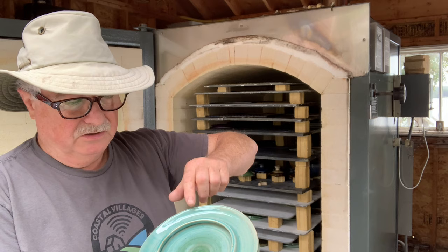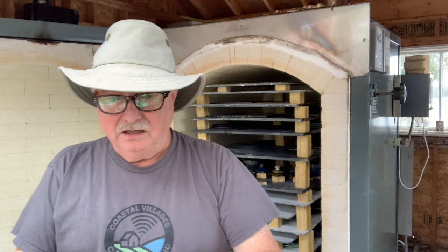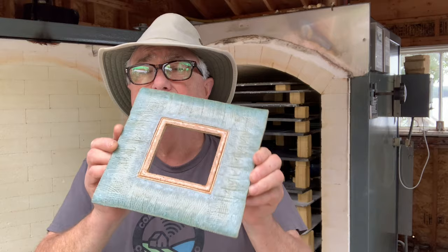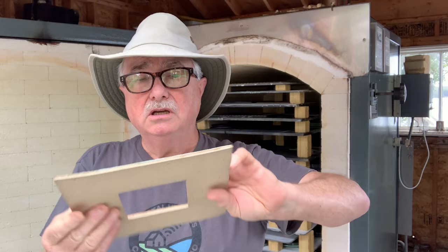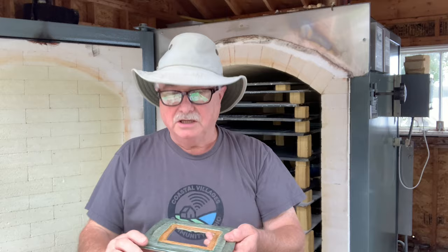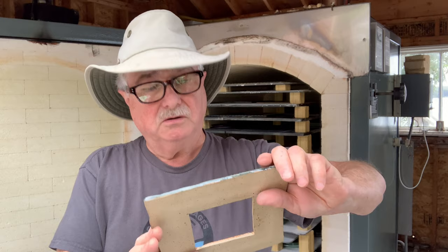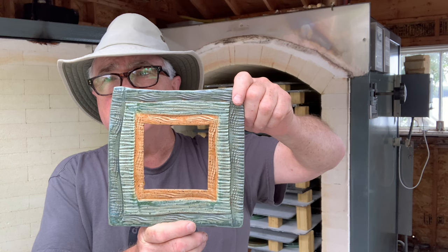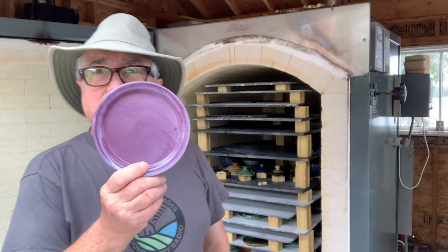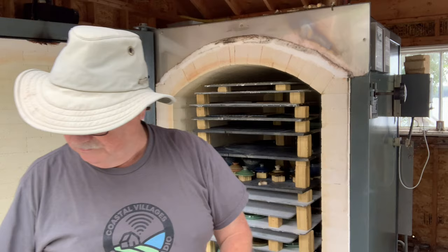On plates like this, you can scrape the knife on the edge of that rim without getting it on the outside edge — that's a good feature of making a little dish to put a dome over the top. Here's the green — it didn't turn out very well the first firing, but this firing it really looks good; it's on speckled clay. A very pretty frame. Here's another one where I used the roller to stretch the frame out and make it uneven — apple green, folk art white, and bright blue over the top of the apple green. Here's that purple — it's an amazing purple, comes out really rich and dark sometimes. I call it rutile green. It's basically my bright blue recipe with rutile and copper carbonate instead of cobalt carbonate.